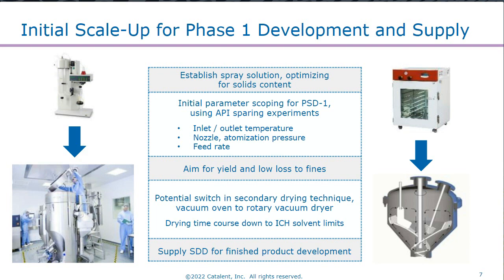Some of the key considerations that we're aiming for here, so because typically API is in limited supply, we want to make good use of that API. So we want to have a clinical manufacturing process that has a good yield and that we're losing little material to the fines. Additionally, as we transfer from the lab to the clinical scale, we also need to consider the secondary drying technique. So how do we drive off the solvents down to acceptable levels for the ICH limits? And we may be switching there from a vacuum oven suitable for small scale work in the lab through to perhaps a rotary vacuum dryer, which can provide a much quicker drying time course.